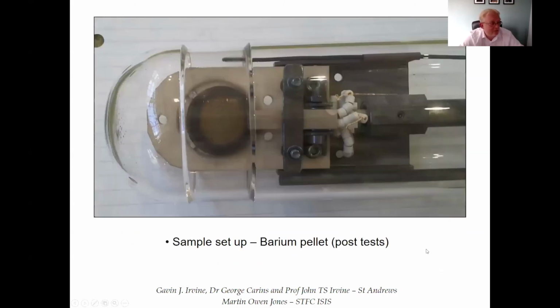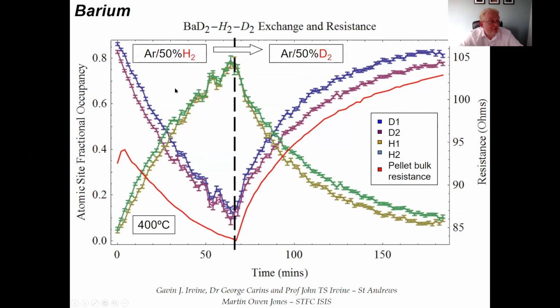So this is what the kit looks like when you actually build it. We have a thin section here to minimize the amount of quartz that sits in front of our sample. We have a simple 4-point probe connected to the surface of the pellet to measure the impedance. And what we see is as we go from hydrogen to deuterium, the pellet resistance decreases, and then increases as we remove the hydrogen and then increase the hydrogen. And this property is related to the fundamental difference between hydrogen and deuterium and its propagation through the material, because the deuterium is twice the weight of the hydrogen.